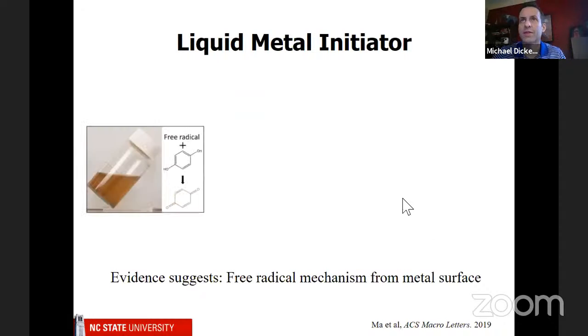So first of all, we did this same experiment in the presence of this black molecule. And this black molecule is known to be a free radical inhibitor. So you may have heard of free radicals, particularly with regard to human health. You don't want to have radicals in your body because radicals are very reactive. And we think that we're creating radicals in this example. Well, this black molecule can actually prevent those radicals from causing polymerization. And when it's working, it will turn orange. And so you can see in this vial, in the presence of this molecule, first of all, it's not a gel. You can see it's liquid-like. So if you tilt it, you can see the liquid. And then secondly, it turns orange, which means that it's forming radicals.